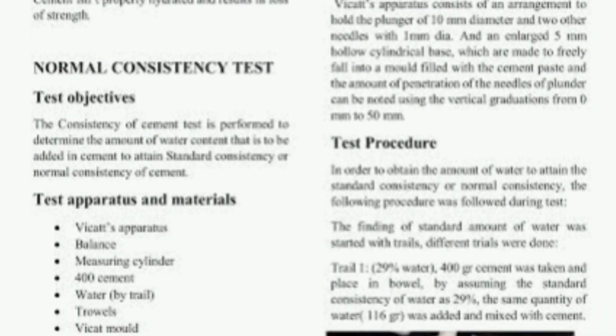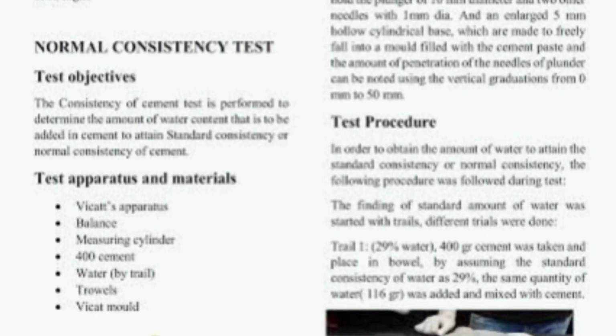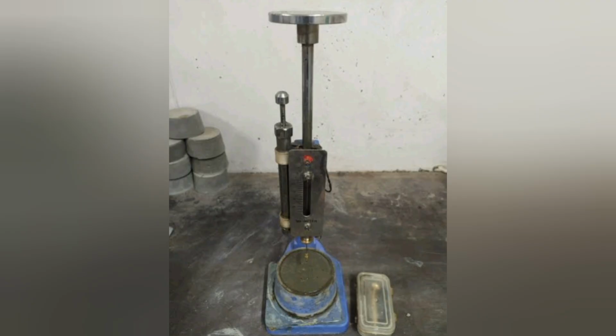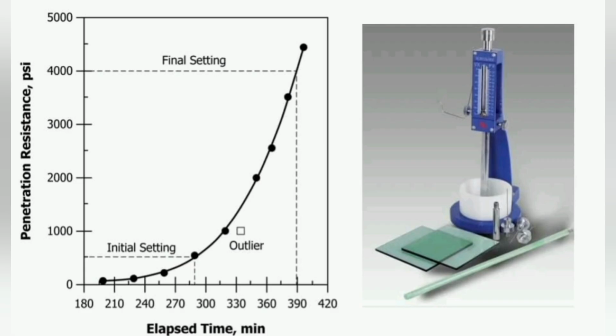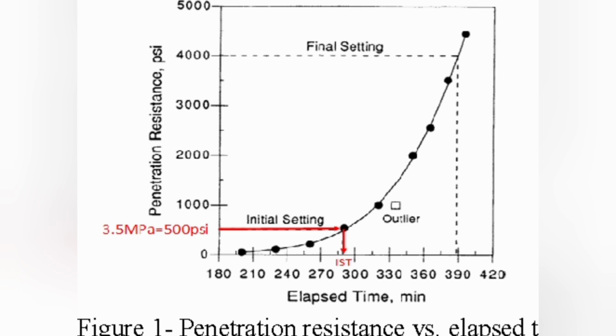We use the Vicat apparatus for this. The goal is to find the amount of water required to form a cement paste of standard consistency. This is defined as the depth to which a 10 mm diameter plunger on the Vicat apparatus penetrates the paste, placed in a mold, to 5 to 7 mm from the bottom. The water percentage required to achieve this, typically around 26 to 33%, is called the standard consistency or normal consistency.